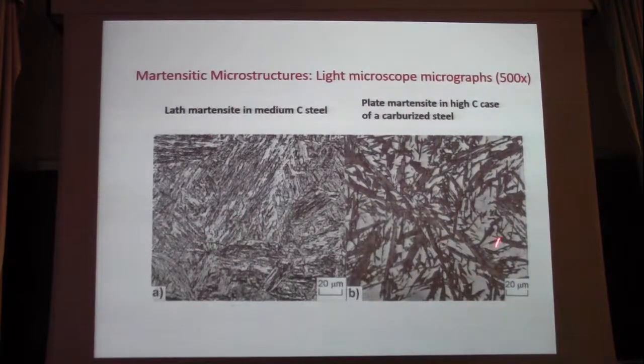And then if you go to higher carbon steels, for example, carburized steels that have 1% carbon, 0.8% carbon, the morphology changes quite a bit. And you get these non-parallel large crystals, and the white areas are the retained austenite that has not transformed during the quenching.